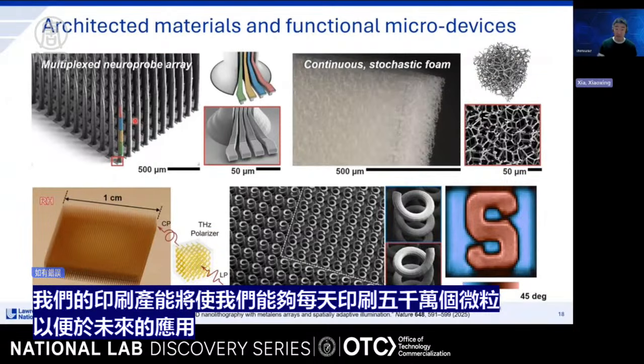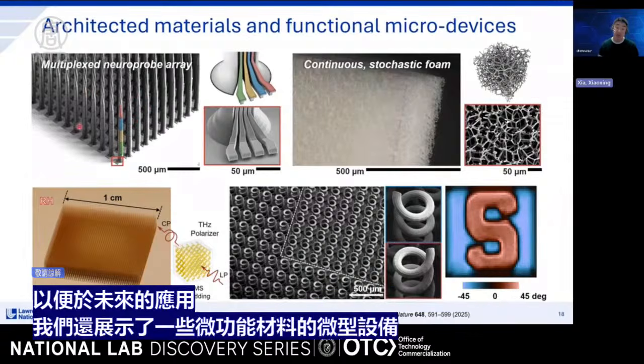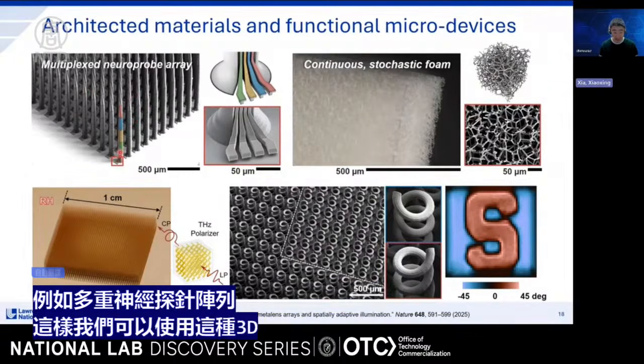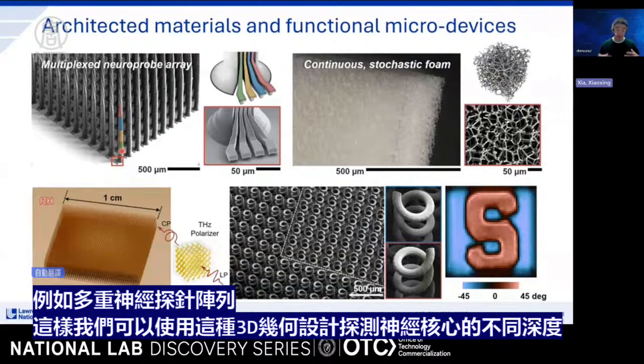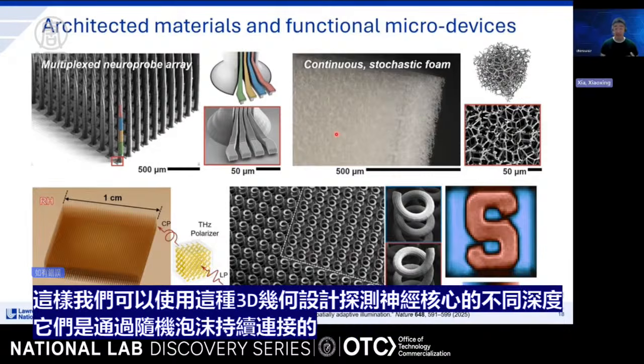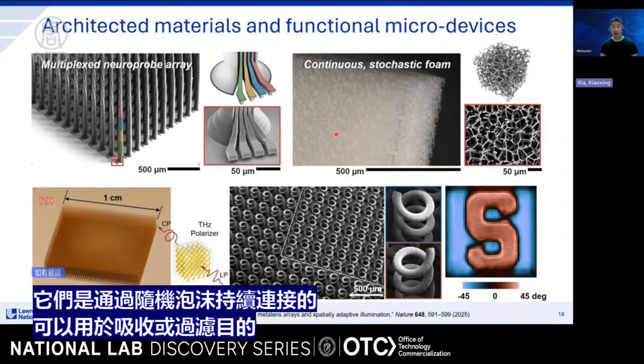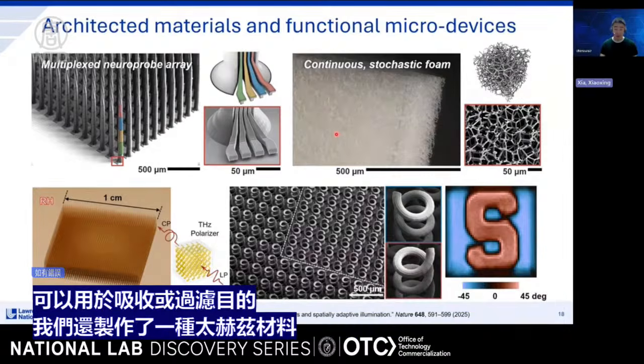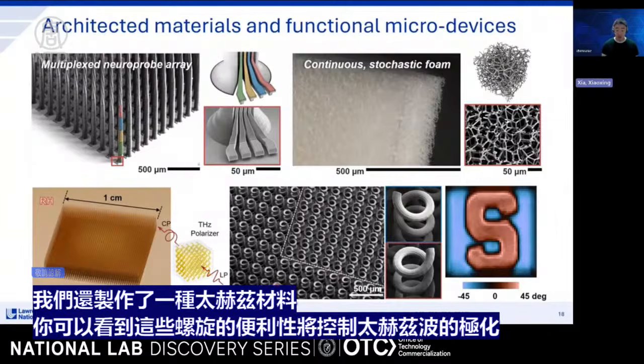And we also demonstrated a few micro functional materials and micro devices, such as a multiplex neural probe array, so we can probe different depths of the neural cortex using this type of 3D geometry design. They are continuously connected by stochastic foam that can be used for absorption or filtering purposes. We also made a terahertz metamaterial. You can see the helix, the handedness of those helices will control the polarization of the terahertz wave.